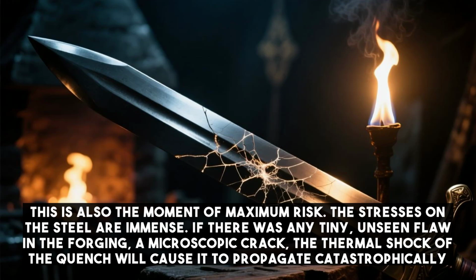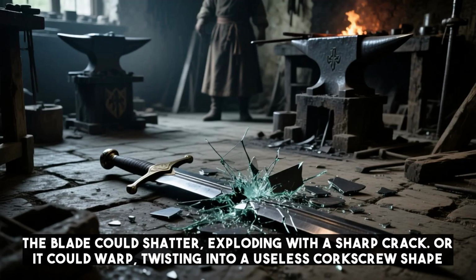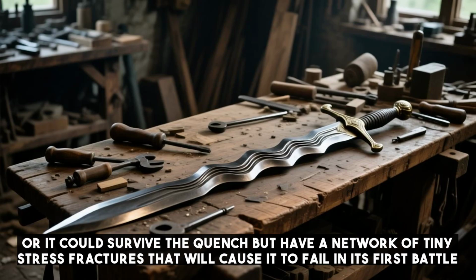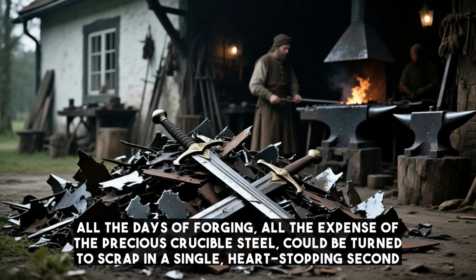If there was any tiny unseen flaw in the forging, a microscopic crack, the thermal shock of the quench will cause it to propagate catastrophically. The blade could shatter, exploding with a sharp crack, or it could warp, twisting into a useless corkscrew shape. Or it could survive the quench, but have a network of tiny stress fractures that will cause it to fail in its first battle. All the days of forging, all the expense of the precious crucible steel could be turned to scrap in a single heart-stopping second.